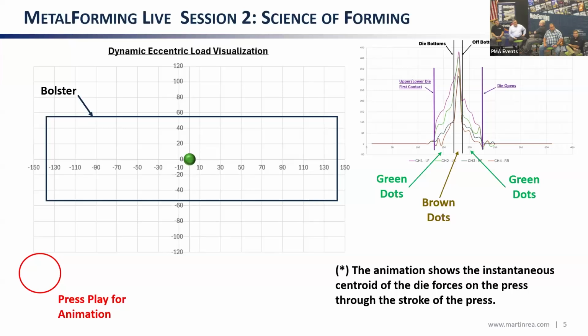The green dots are in play after the die makes contact with the blank holder, and you can see the load start off in this transfer press very far to the left, on the feed side of the press. You can see the load transfer. It bottoms, and as the die unloads, you can see the shift in the centroid through the stroke. I'm going to try to do that one more time.